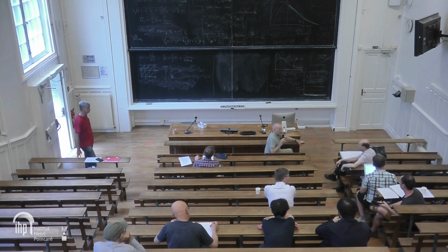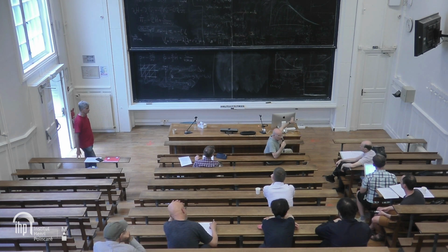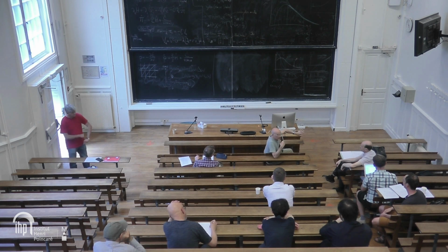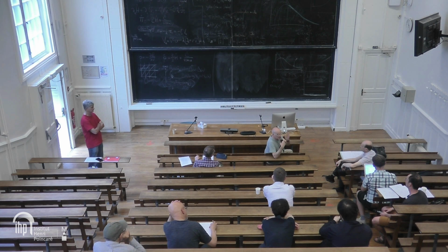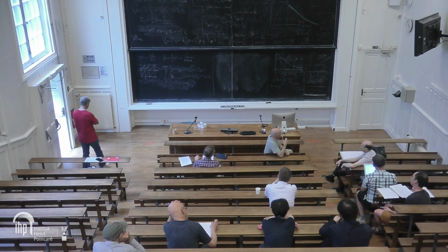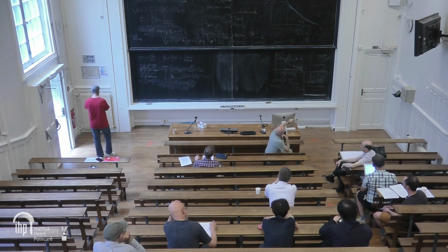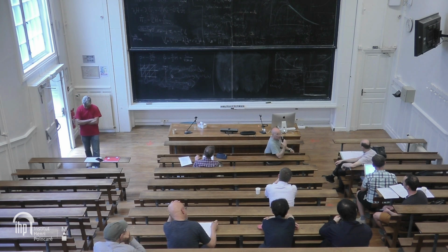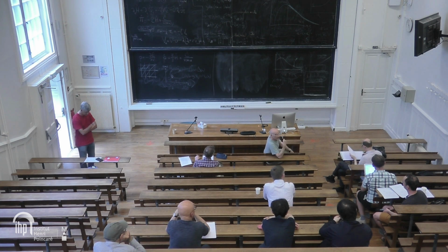Maybe I can elaborate on this. Of course I was very sketchy. There are many, many flavors of diagrammatic Monte Carlo, and in all the studies that I alluded to, even in the non-ordered states, optimizing the starting point proved to be extremely important. That's how we could get the pseudogap for the first time in these kinds of schemes. And indeed, if you want to go into the ordered state, you have to start from a symmetry broken state or expand around that.